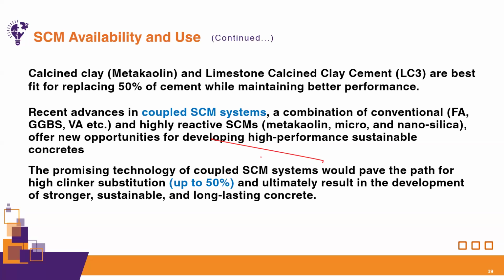And there is another option, which is the coupled SCM system. What is this? It is a combination of conventional SCMs, which are moderately reactive, with highly reactive SCMs like metakaolin, micro and nanosilica. So if we use these together, we can replace the clinker by a high amount, up to 50%, without compromising on the strength and durability performance. So the promising technology of the coupled SCM system would pave the path for high clinker substitution and ultimately result in the development of stronger, sustainable, and long-lasting concrete.